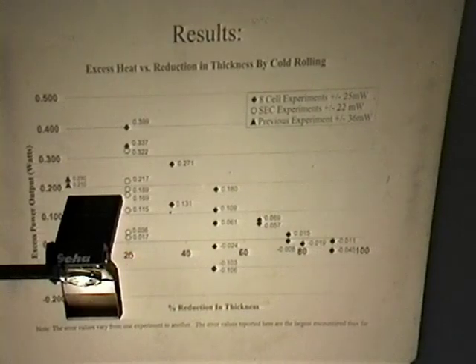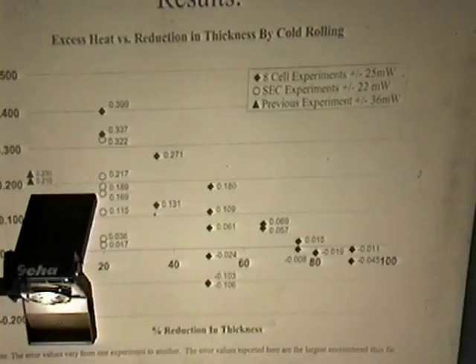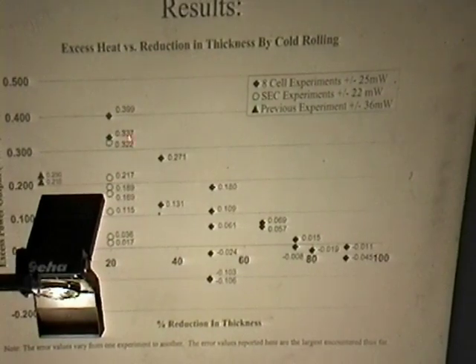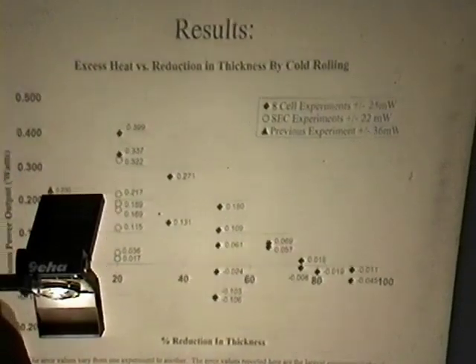If you start to reduce the thickness of the cathode by cold rolling, you see that the 8 cell experiments gave the greatest excess heat results. As you increase the cold rolling, the excess heat decreased. Now, we concentrated on this area because it looked interesting with the SEC, and we found that 8 out of 10 experimental cells showed excess heat.